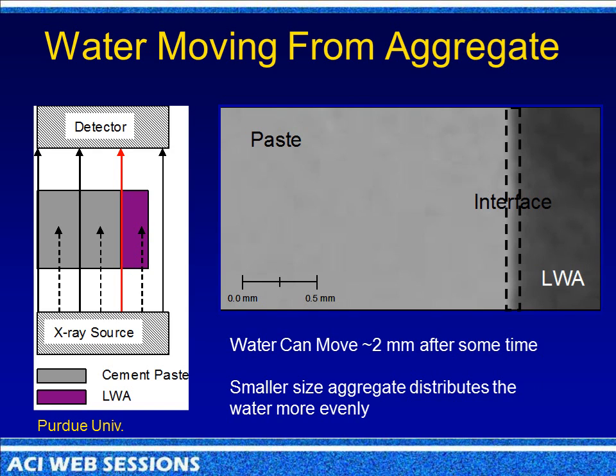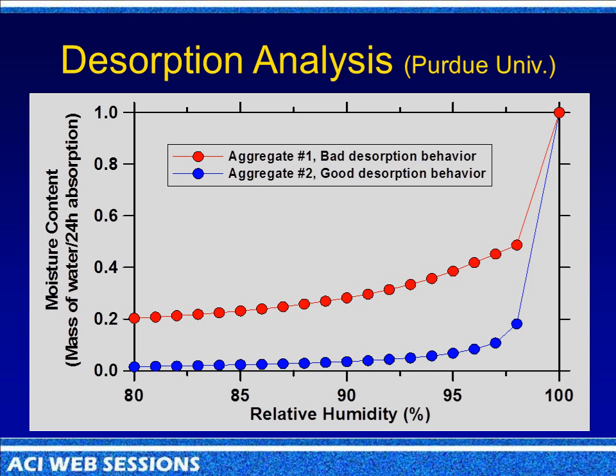Now, here we go. Look at this. Lightweight aggregate, as it comes out, the water comes out. It comes out about 2 millimeters. It comes into the paste. And this is the transition zone where you get the internal curing. Now, as it comes out, this curve shows you the desorption curve. And the blue line shows you aggregates that give you a lot better internal curing than the red line.